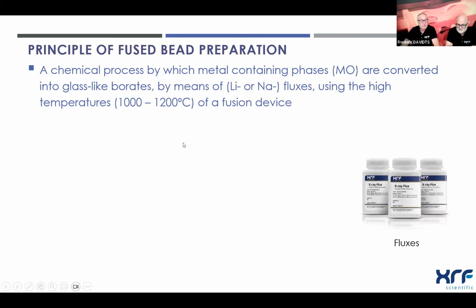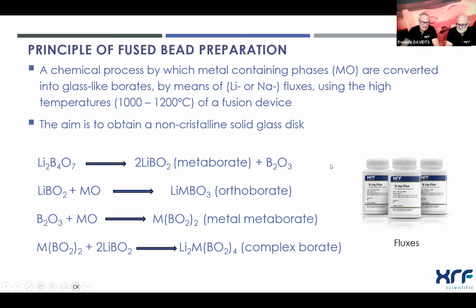And of course, we will also use a high-temperature fusion device. Actually today we still have it up to 1,200 degrees, but today we already have systems available up to 1,300 degrees. But it is important that we obtain a non-crystalline solid glass disc. And this is more or less the reaction that takes place.